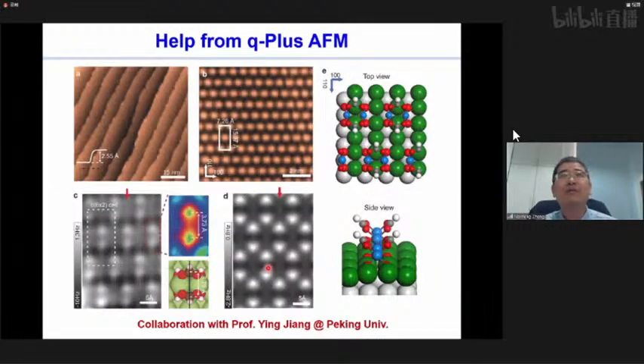The reason we were able to really understand how those formates form passivation layers on the copper surface is because we had the help of Q+ AFM, which helped us identify the bonding structure, the coordination bonding structure of the formates on copper. And with this binding structure information, we can get a deep understanding of why this surface is good for anti-oxidation.